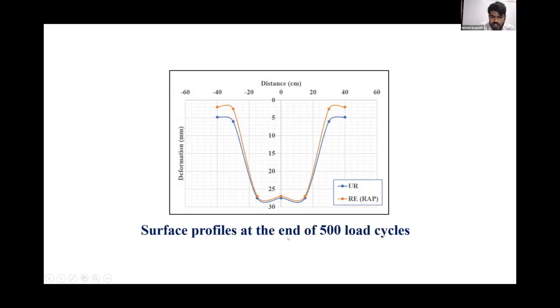The surface profiles at the end of 500 loading cycles. These readings were obtained from the dial gauge settlement readings. Here we have shown plate width B, and B by 3. It is 15 plus 15, 30 centimeter. The settlement at the loading point is observed to be 27 mm, almost the same in both the cases.